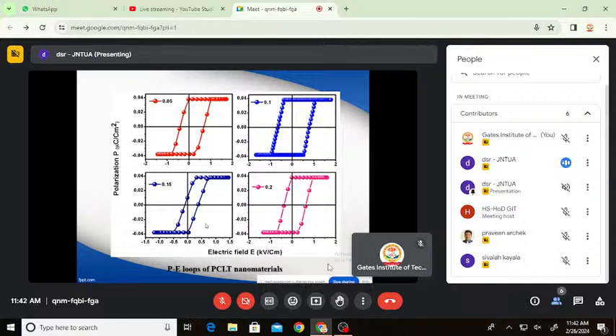From the UV visible spectra, it is observed that the energy gap varies between 0.32 to 3.2 electron volts, and dielectric properties like epsilon dash and epsilon double dash were studied as a function of frequency. Both these parameters exhibited large values at small frequencies, and the hysteresis loops were also noted. From this, it is observed that they showed a high value of coercive field.